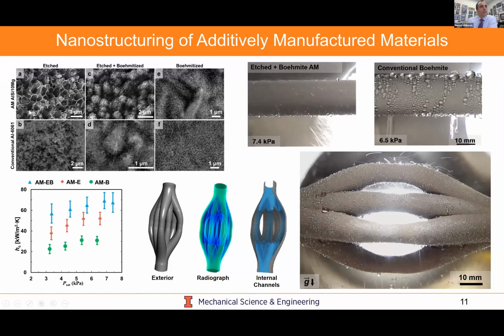And interestingly, it turns out that some additively manufactured materials give you better opportunities when compared to conventional materials. So for example, if you use crystallographic etching, you could see that you have these cellular-like honeycomb structures that form on the surface. These are actually really good at preventing liquid propagation laterally and enhancing droplet jumping. And you see this here through the video. This is an additively manufactured tube, and this is the conventional tube. And you clearly see water shedding. It's just through the roof.